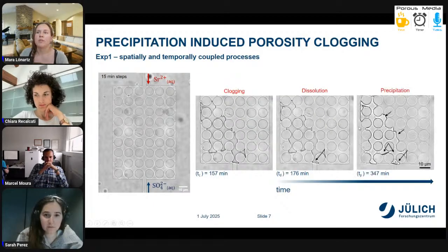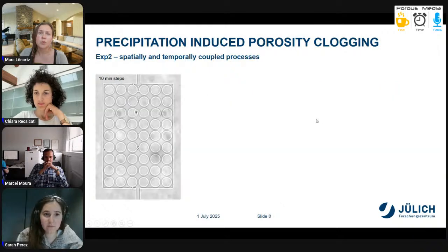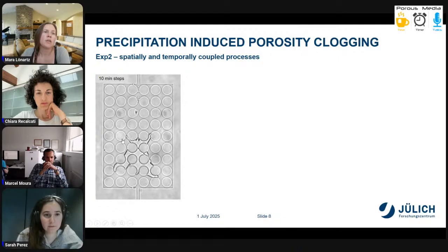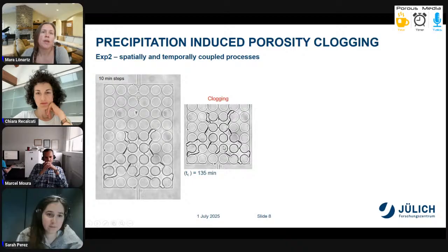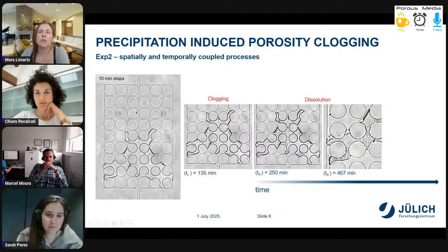enabling further precipitation reactions. In the second experiment, we could see that the nucleation and growth of celestine started even more in line with the expectation, in the sense that it was even more in the center and symmetric part of the chamber. And again, the celestine is growing, clogging the chamber. And due to the inhibited mixing of the reactants, we can see dissolution and a kind of microporosity forming